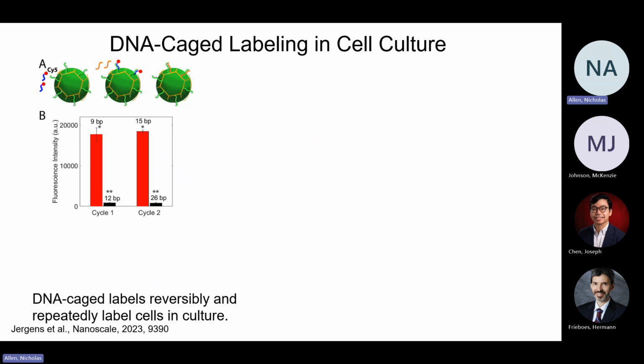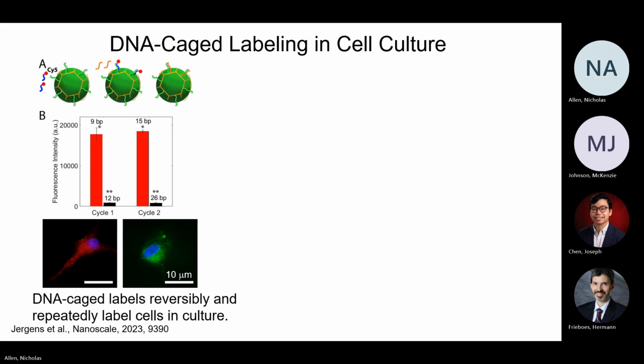So then we did label erase experiments. So here we are just in solution. We're adding a DNA that has a fluorophore on the end. It's binding cage and we're erasing it. And we did multiple cycles by using increasing base pairing lengths. And we found that our erase step was around 95%, with 5% residual signal.